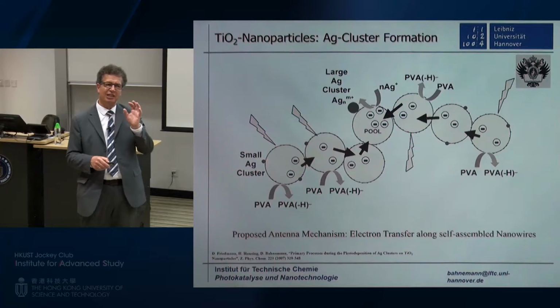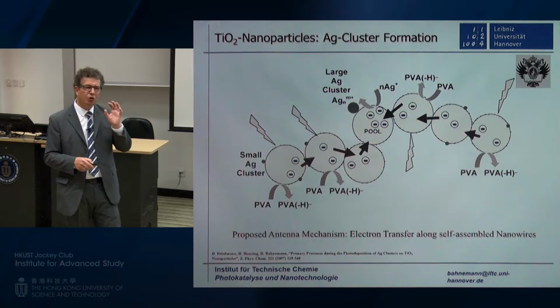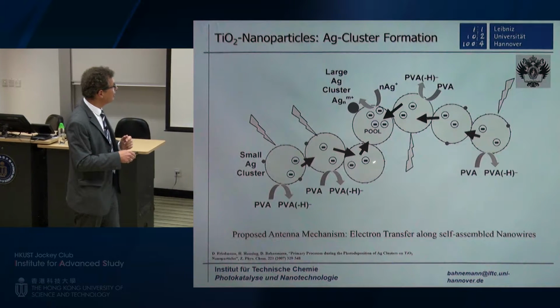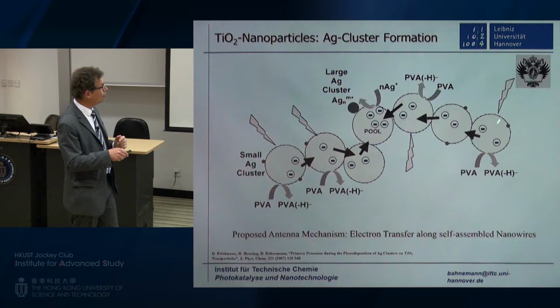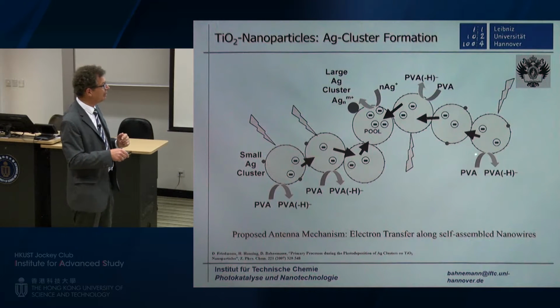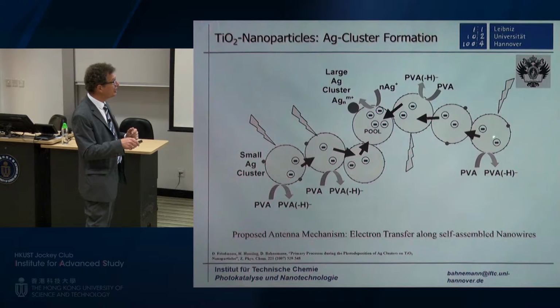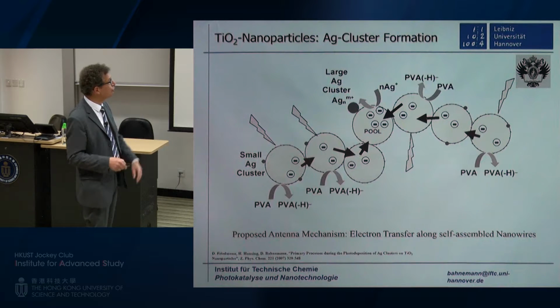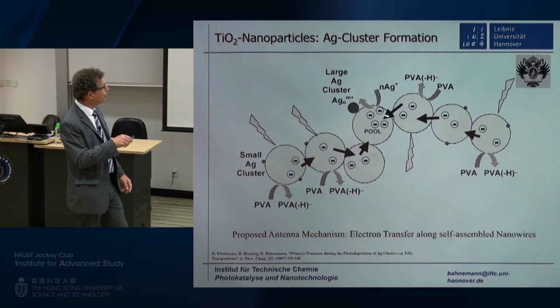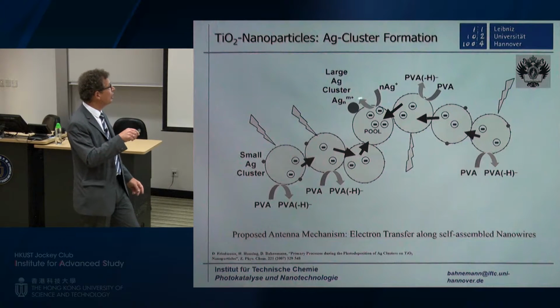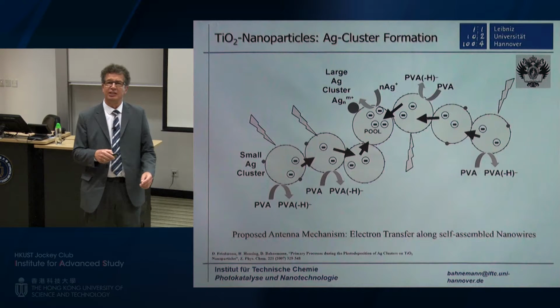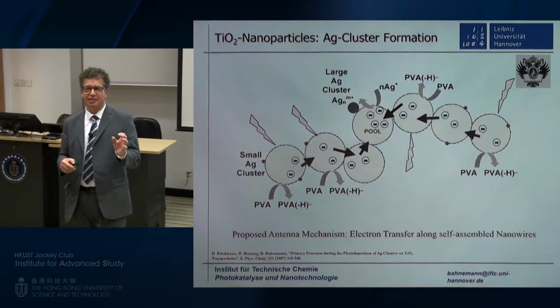You already have these clusters. And this can only happen because each particle only absorbs about 1 photon in our experiments. So you only have 2 charges here. So you must envisage a migration now of charges along this 3-dimensional network, along these nanowires, and then you have a pool now of electrons that can be transferred all together to form these larger silver clusters in this system.